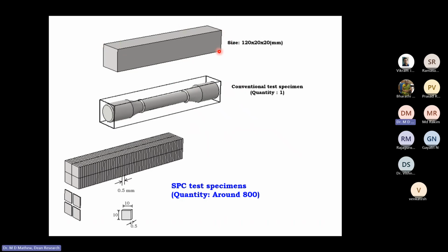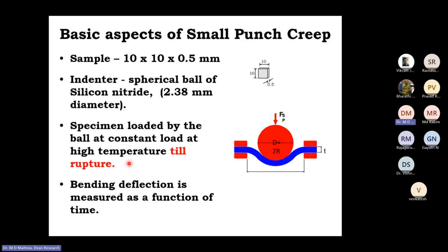This is a block of 120 by 20 by 20. Out of that, I can prepare one conventional creep test specimen meeting ASTM standard. But when I am talking of small punch creep test, I'll be able to generate 800 samples from this single block, because the size of a small punch creep specimen is only 10 by 10, and this cross section is 20 by 20. I need only 10 by 10, and the thickness of the specimen is just 0.5 mm. So just one block of 120 by 20 by 20 can generate 800 small punch creep samples. So that is why I say it is material non-intensive.